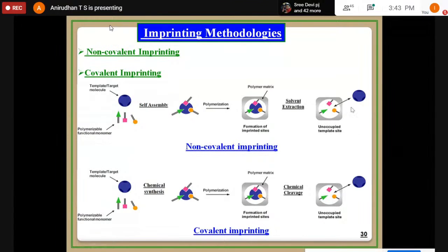And so what happens here? Then when you introduce a solution containing your template, that template only penetrates and accumulates inside this material, because we have created a shadow of that particular template. So after leaching your template, when you introduce this material in any sample containing that template, even in the presence of hundreds and hundreds of other chemicals, that template only accommodates in that particular cavity, because that cavity has a shape similar to this template. And this is the technique that we have introduced.